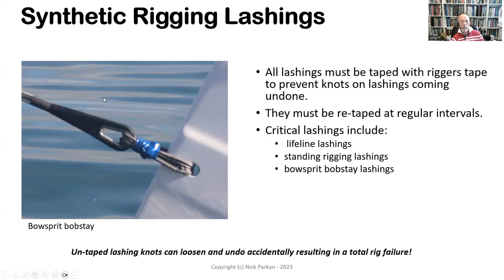Again, in terms of safety of synthetic rigging, typically we use lashings which are tied off. Again, these must be taped to prevent the knots from coming undone, because typically synthetic rope rigging doesn't hold a knot very well because it's very slippery material. The Spectra or Dyneema that it's made of is naturally very slippery, and so they must be taped to ensure that the knots don't work loose, and then of course they must be retaped at regular intervals.